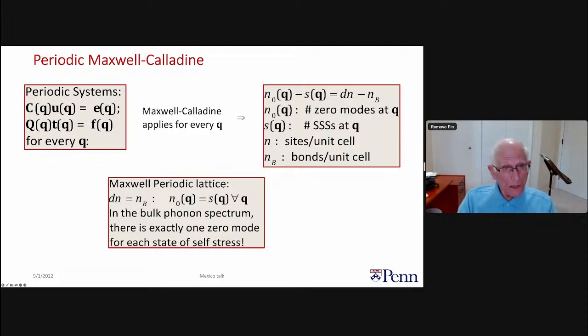For a Maxwell periodic lattice, so this is one where we go to periodic boundary conditions, so there are no edges, then we have dn is exactly equal to n_B, that's the number of bonds per unit cell, and N0 of Q for every Q is equal to S of Q in the bulk phonon spectrum. So there's exactly one zero mode for each state of self-stress, which will not be the case when we introduce edges.